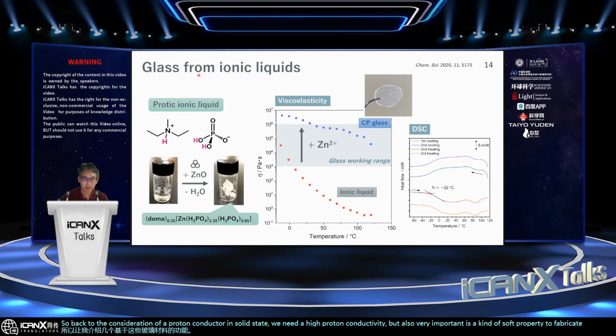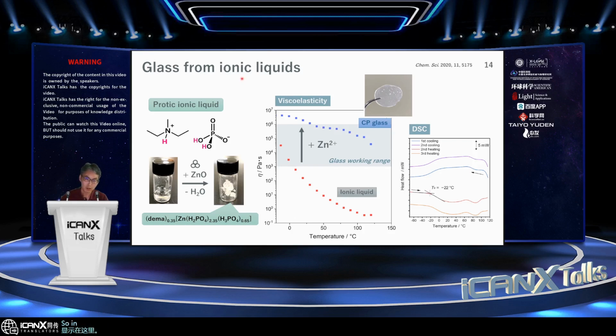One design of a proton conductive glass is shown here. In this case, we also utilized ionic liquids, which are organic cation-anion salts whose melting temperature is below 100 degrees C. One example of a proton conducting ionic liquid is shown here, okay? The pink proton can work as a proton conductor, and this cation and anion form the ionic liquid here, okay?